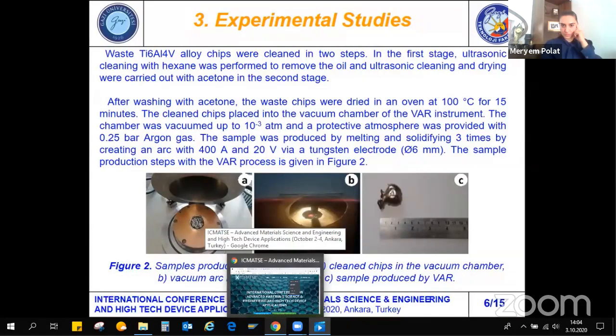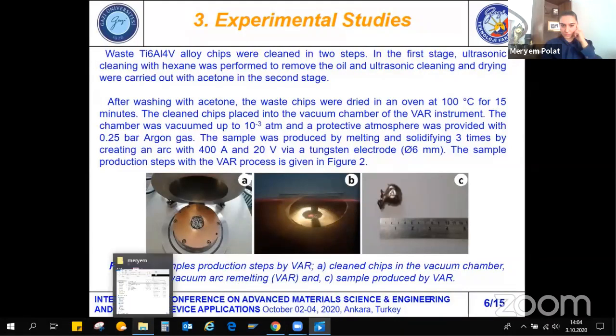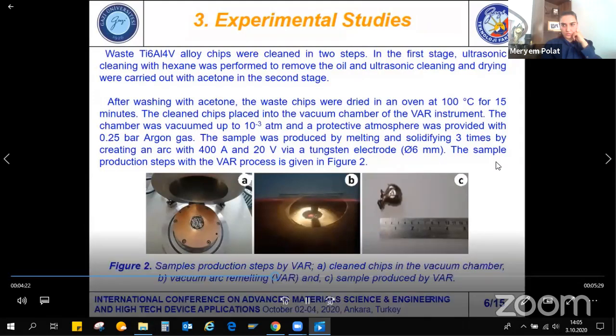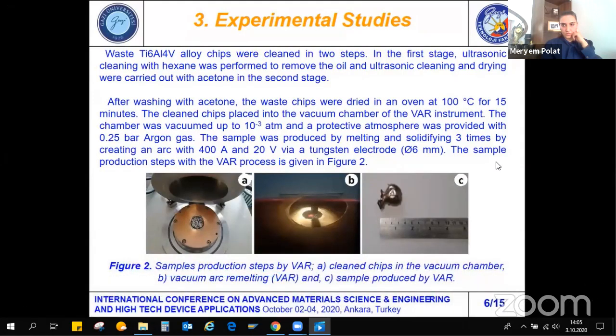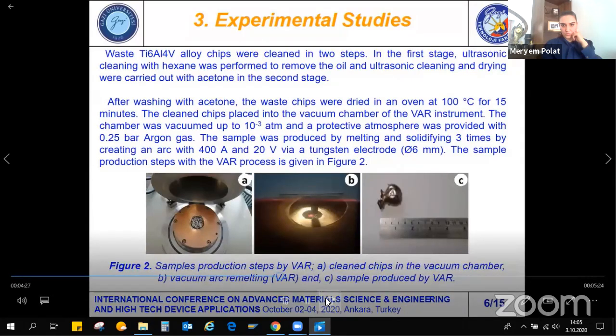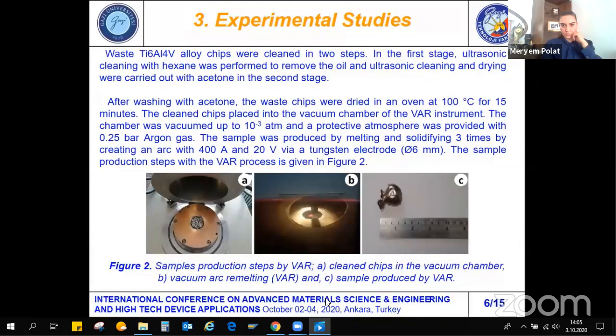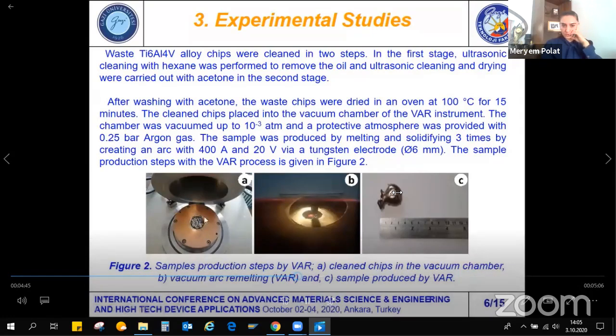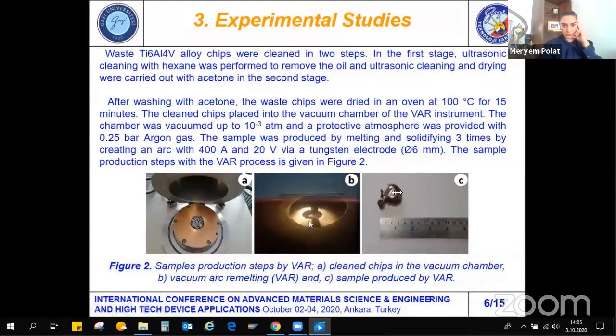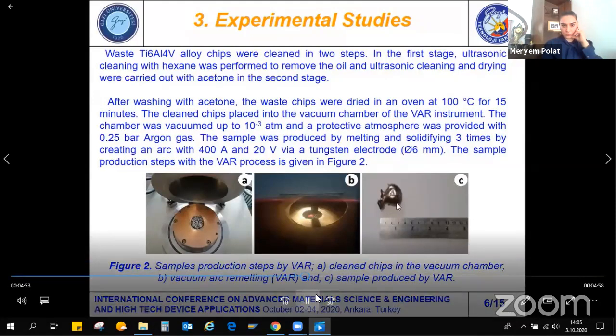The cleaned chips were placed in the vacuum chamber of the vacuum arc remelting instrument. The chamber was vacuumed up to 10 to the -3 atm, and the protective atmosphere was provided with 0.25 bar argon gas. The sample was produced by melting and solidifying 3 times by creating an arc with 400 ampere and 20 volts with a 6 mm tungsten electrode. The sample production steps with the vacuum arc remelting process are given in Fig 2. As you can see here, the vacuum chamber, during remelting, and our samples produced by vacuum arc remelting.